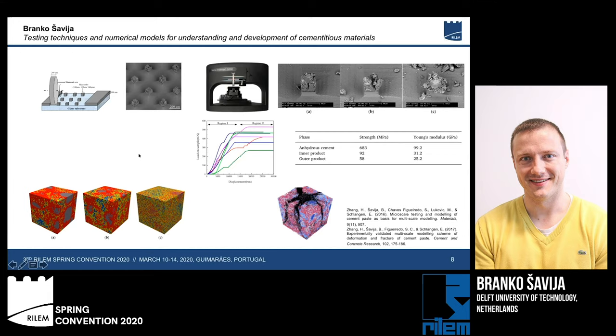Now, except the cement paste, we also need to know what is happening at the aggregate cement paste interface, the so-called ITZ zone. So we use a similar approach using, again, a micro-dicing saw. We can prepare specimens that contain part hardened cement paste on aggregate substrate. But because we want to know the tensile properties of this zone, we will now subject these materials to bending.